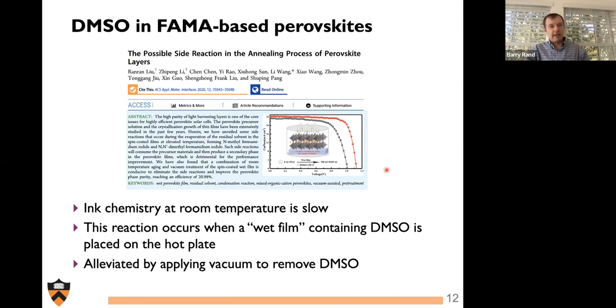In our experience, one, this vacuum process wasn't particularly amenable to upscaling and commercialization pursuits, but two, the remnant DMSO that's trapped at the bottom of the film, and folks from Jinsong Huang's group have seen a similar thing happen, whatever's trapped in the bottom of the film tends to stick around there, and it's very hard to remove. And so this annealing process wasn't necessarily a panacea that could be generally applied.